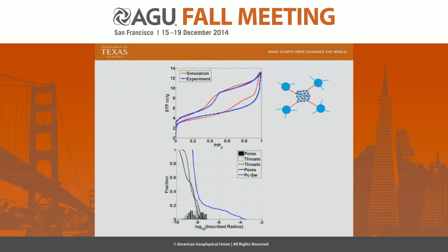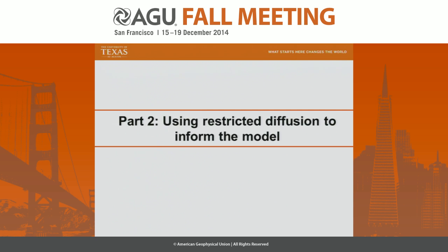But also bear in mind that this whole natural sorption hysteresis story is only applicable to pores smaller than 100 nanometers, because beyond that, capillary condensation is not as relevant anymore, and therefore it needs to be looked at as a supplemental method, along with images and other measurements such as capillary pressure to incorporate much larger scale pores.